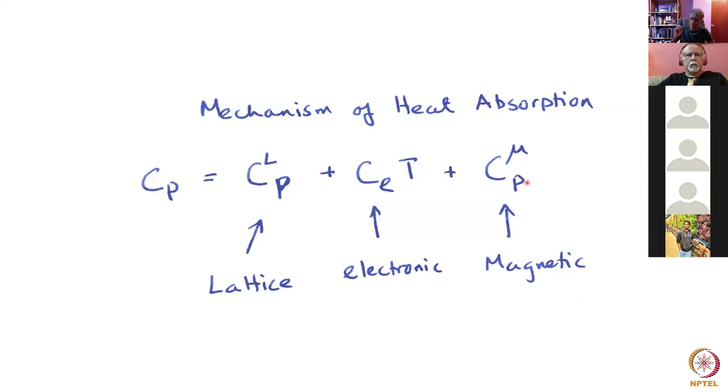Now, I will repeat this many times in this series of lectures, but in the case of iron, body-centered cubic iron, if we did not have this term here, ferromagnetic to paramagnetic disordering as we go beyond the Curie temperature, then we would not have body-centered cubic iron stable at ambient temperature and pressure. Now just imagine your life without body-centered cubic iron. It would be absolutely miserable. So you owe magnetism for civilization in your lives.